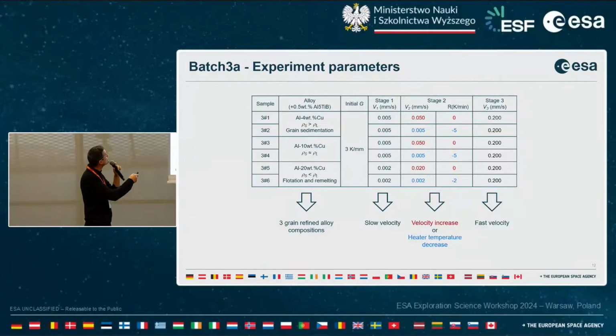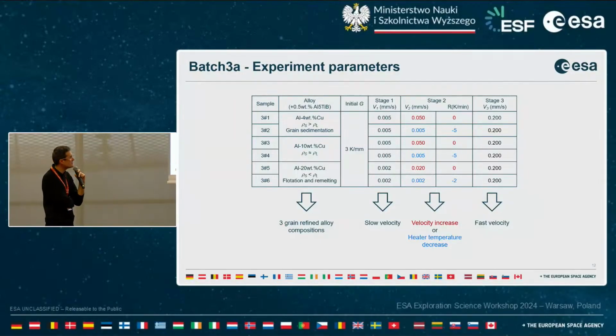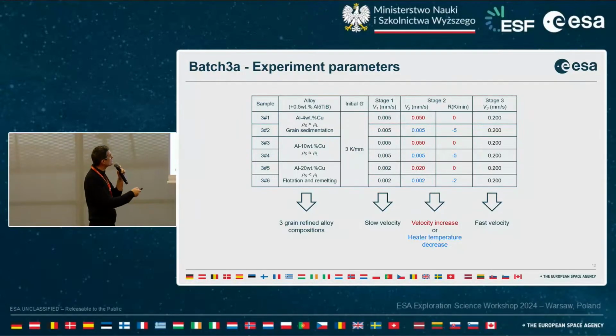Then I will go to batch 3A experiment parameters. So these are more recent experiments. The samples were retrieved in 2021. And you can see here a table of all these experiments carried out on aluminum copper alloys. So to summarize, 3 grain refined alloys were studied. We triggered the CET by applying a slow velocity, then either a velocity increase or a decrease of the heater temperature. And all the experiments finished with a fast velocity.